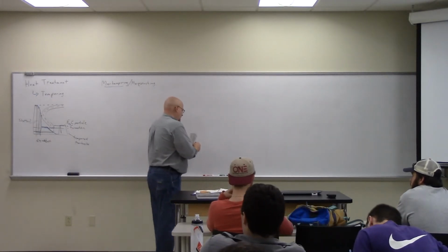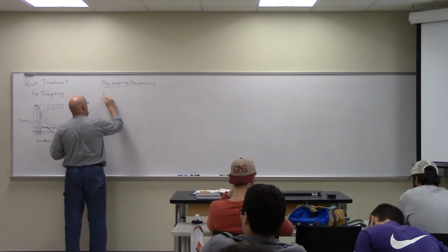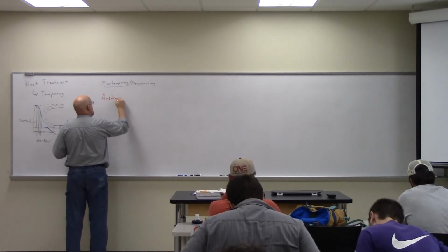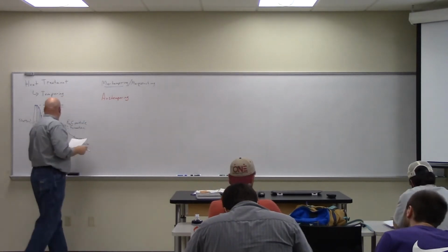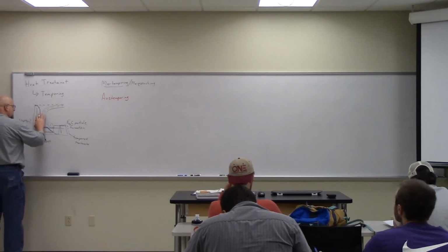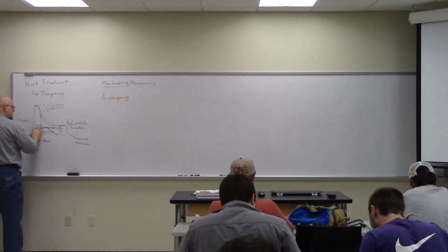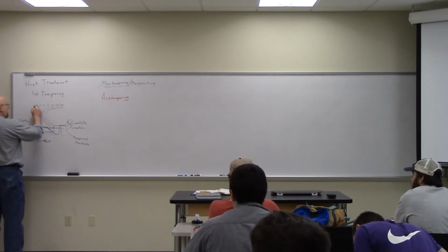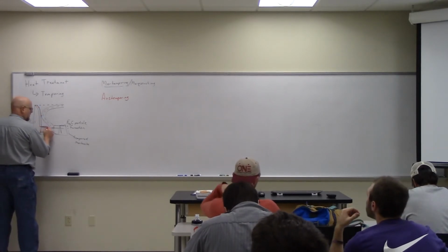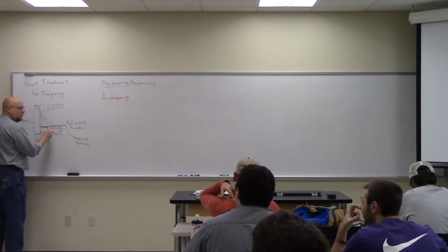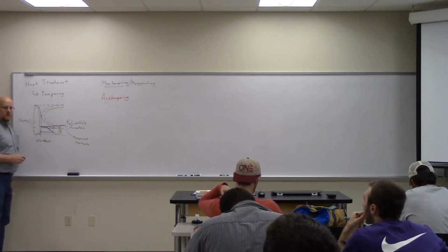Then another possibility is Aus tempering. And Aus tempering, getting too many lines on here. Okay. Aus tempering, again, avoid the knee, but then you can just basically let it all completely convert to bainite, but just barely above the martensitic transformation. So you get as fine a bainite as possible, and then bring it down.